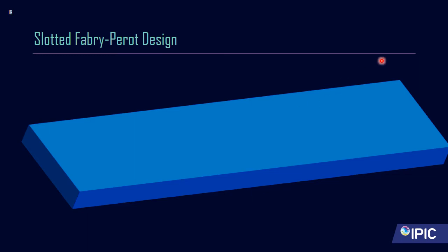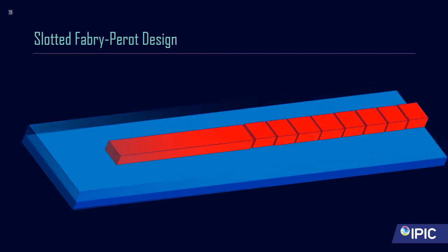So, we begin with just a simple wafer. This wafer involves all the layers we need to create a laser, including the active layer, somewhere in the middle. So what we do is we etch, exposing just this ridge section, and we remove the slots in between. So here is the gain section, or Fabry-Perot section, and here is just the slotted section.